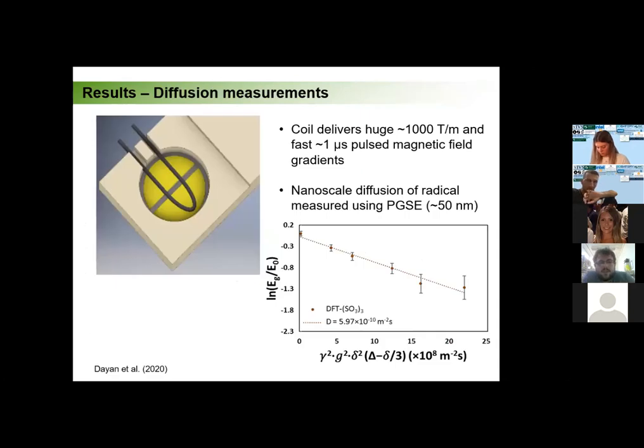Another application is diffusion measurements. If we take the system that I showed and we add the gradient coil, here, this is a copper coil, we can actually use this coil to deliver pulsed magnetic field gradients. And what does it mean, gradients? It means that there's a high magnetic field here and a low magnetic field here. So there's actually a spatial difference of magnetic fields that the sample feels.